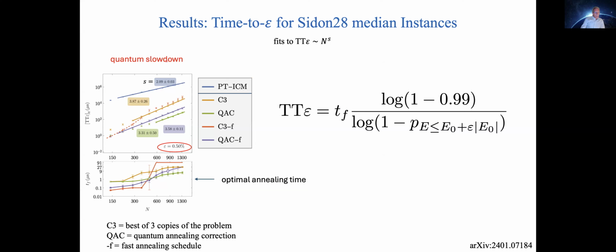So what I'm showing you here is, first of all, remember epsilon, remember the optimality gap. So here is the time to epsilon as a function of problem size, for epsilon of 0.5%. And the bottom plot is essentially a proof that we're able to optimize the anneal time. So every time you see a circle, that means we found the optimal anneal time, and that is its value. And the different colors here: PT-ICM is in blue, and that's the classical algorithm. And then the other four are the quantum algorithms with QAC, the quantum annealing correction, C3, the three classical copies, and then -F means using a fast annealing schedule.